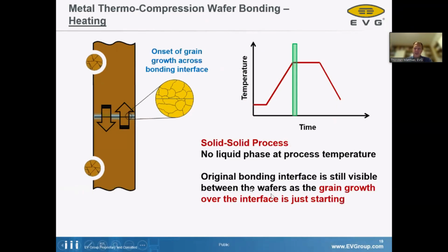Okay. So once we start heating up, basically we start to see metal ion diffusion. Typically the diffusion path is across our grain boundaries, which is kind of the diffusion highway in a metal system. And the engineers typically use this as a means to assess whether the bonding has been good, whether there has been a reasonable enough material transfer from one surface to another, if we actually start to see grain boundary growth across the bonding interface. That basically, if you do an interface cross-section, you would not see this line of the bond interface at all anymore. This would be your way to determine that you basically have a void-free bonding, that you have a mechanical and also a stable and hermetic seal ring on your device.